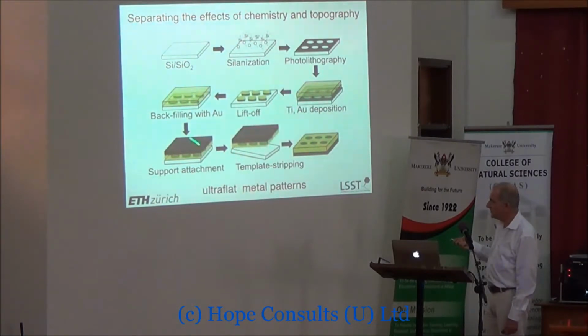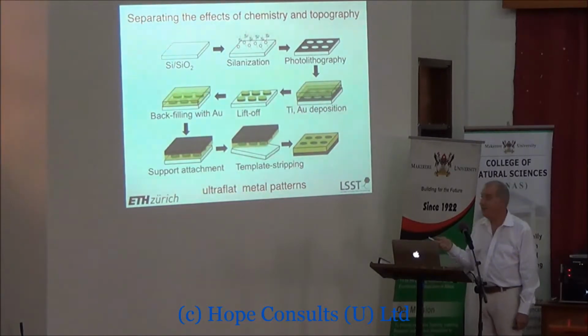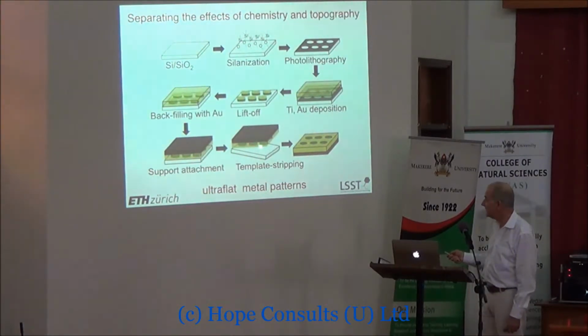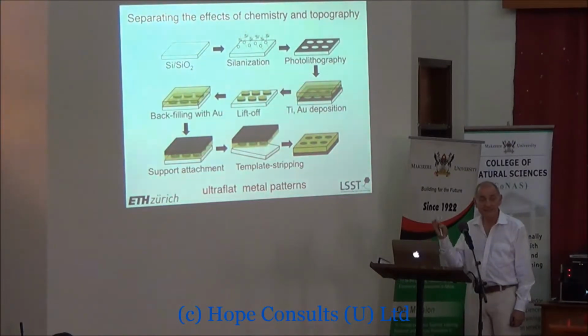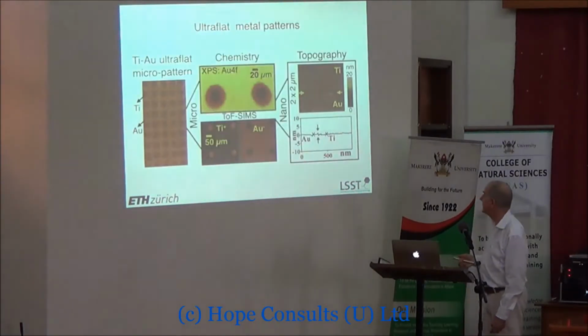And then we put some sort of support on the back of it. And then we turn the whole thing upside down, and we take off the initial silicon wafer that we used, which gave it a flat surface. So we've got a super flat surface under there. So it's now turned upside down. Here's the surface that used to be in contact with the silicon wafer, and we have a pattern of titanium within a gold background. And titanium and gold have completely different surface chemistries, so we can functionalize them in completely complementary and orthogonal ways at the same time. And this just shows the surface we made.